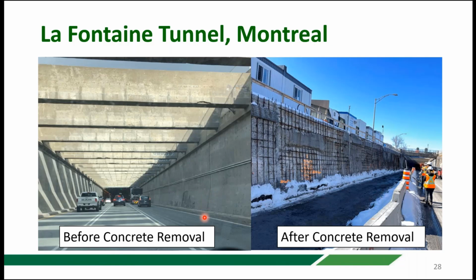But here's a picture at the north entrance, where you're driving down into the tunnel, and you can see along the walls before it goes underground, you can see some localized damage, but unless you go out and do a hammer survey or whatever, it maybe doesn't look all that bad. And then over on the right is essentially the same section, or just up from the same section. And you can see there's a lot of delaminated concrete there that was removed, obviously prior to the concrete replacement work going on.